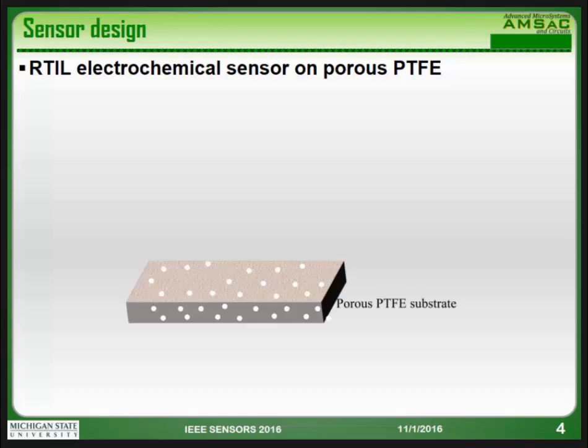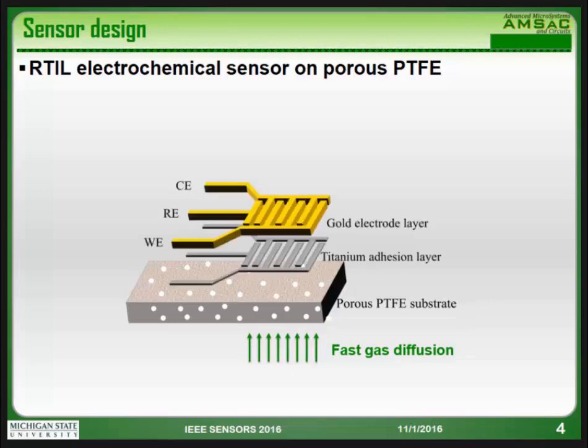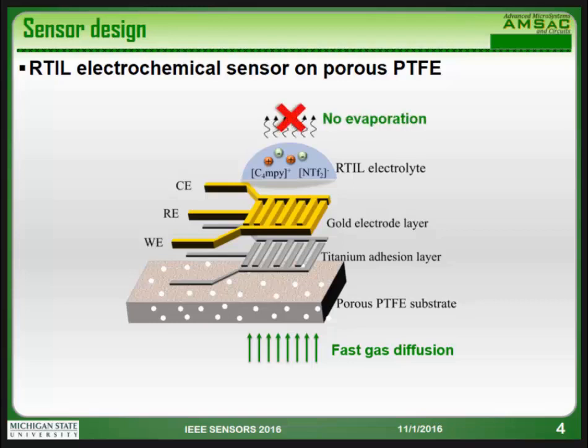First, this is a schematic of our sensor structure. Here shows the porous PTFE substrate, and in our design, the gas will diffuse through the backside of the substrate instead of the electrolyte. Then we use photolithography to pattern the gold electrode and the titanium adhesion layer on the substrate. Then we coat the room temperature ionic liquid on the sensing area. And for this electrolyte we want to emphasize that there's no evaporation.